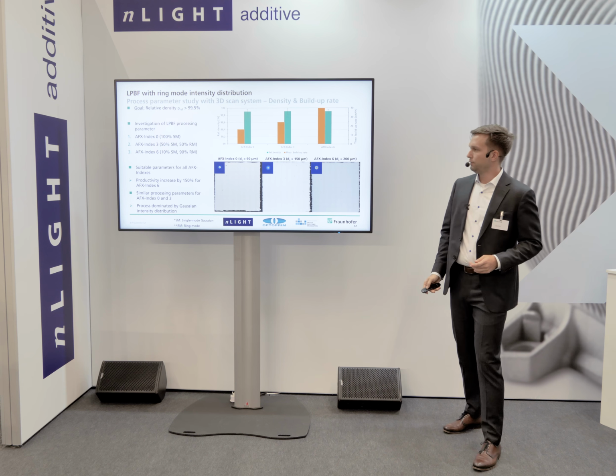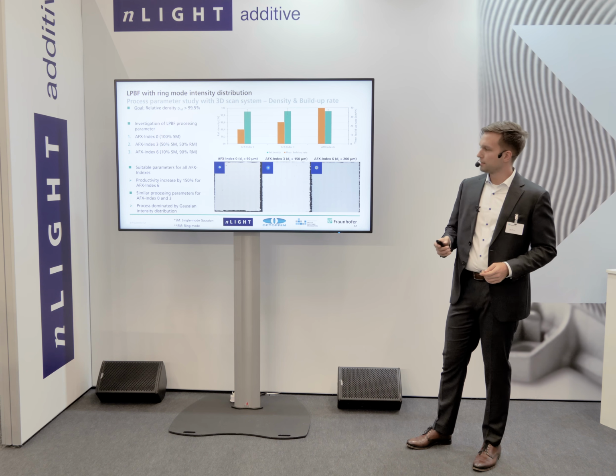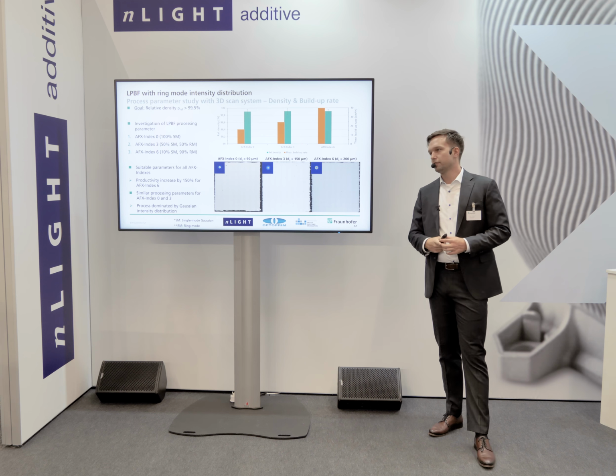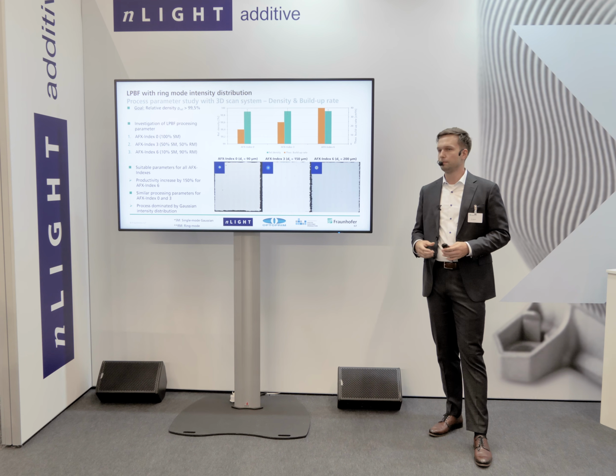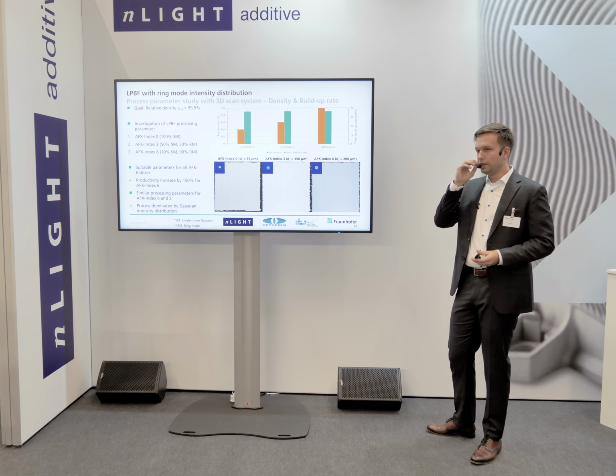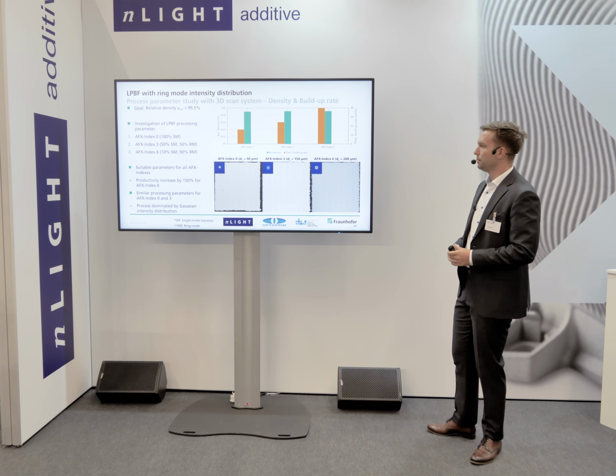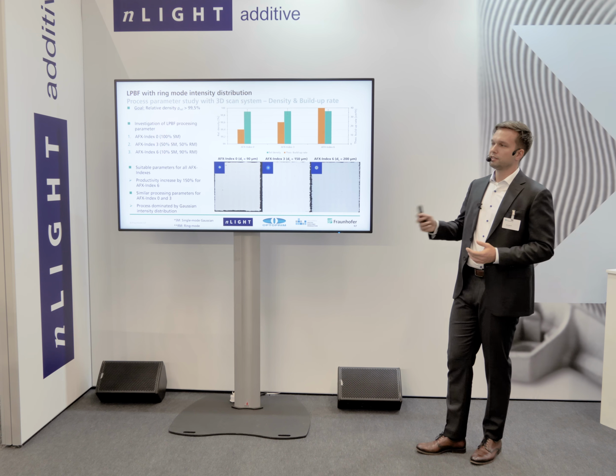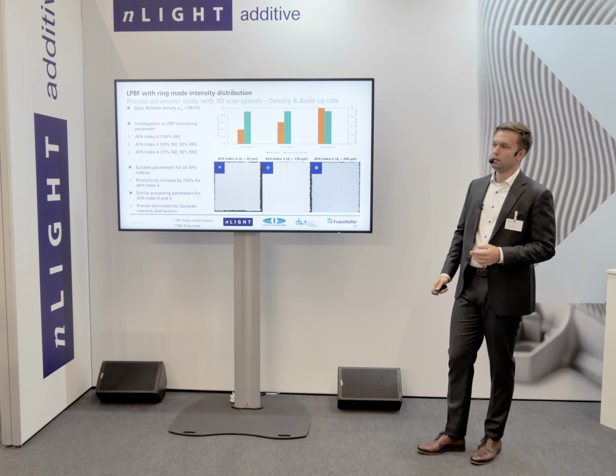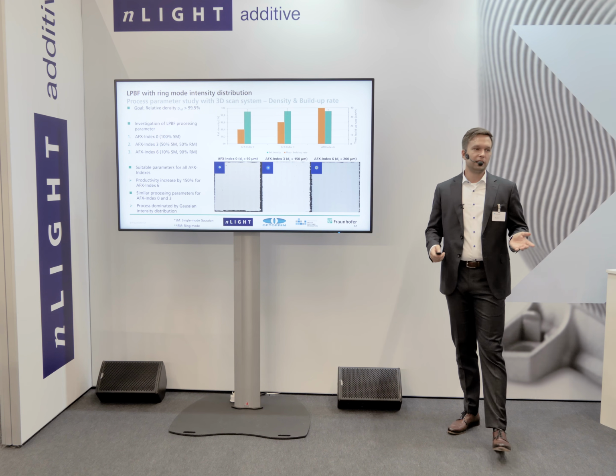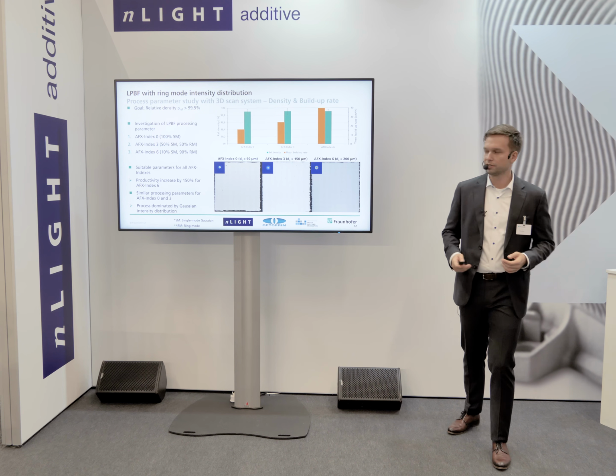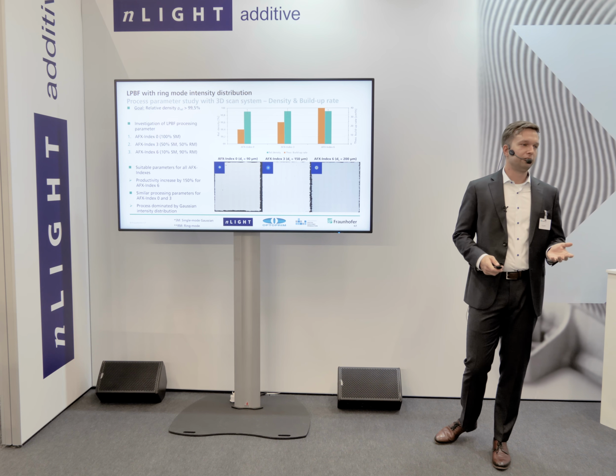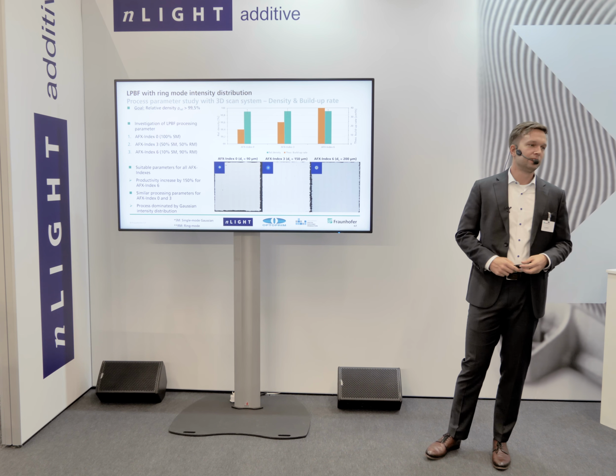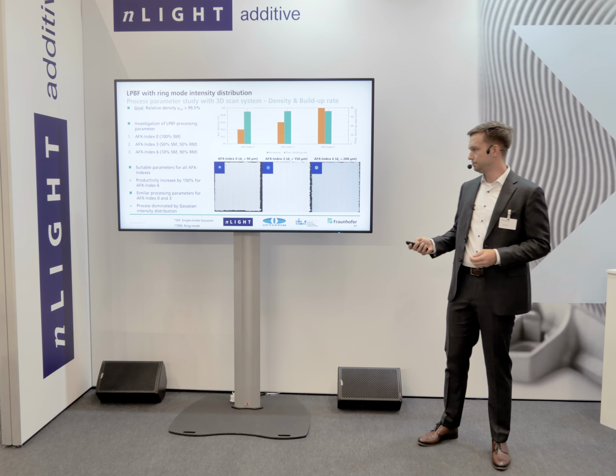However, the AFX index 6 allows us a scaling of the productivity by a factor of 2.5 compared to the single mode Gaussian, which is really quite impressive, because through just switching the intensity profile, we suddenly have the tool to really have high productivity L-PBF processes, and we still have the flexibility that comes with the single mode Gaussian beam.